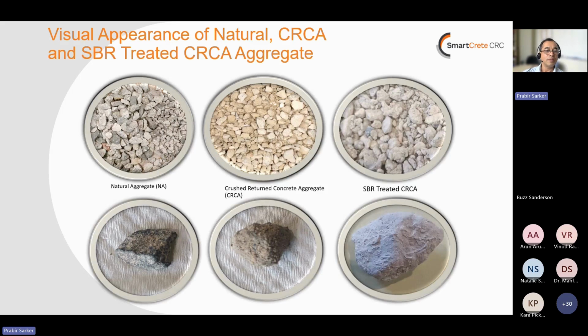So we can say this is the natural aggregate, CRCA aggregate, and SBR latex treated aggregate. So prior to the treatment, it had loose adhered mortar on it, which has become a more compacted, more improved adhered mortar on the surface of the recycled aggregate. So this is a close view. If it is fully covered by the latex, then the aggregate can turn into this. So from this appearance, it can turn into this appearance.